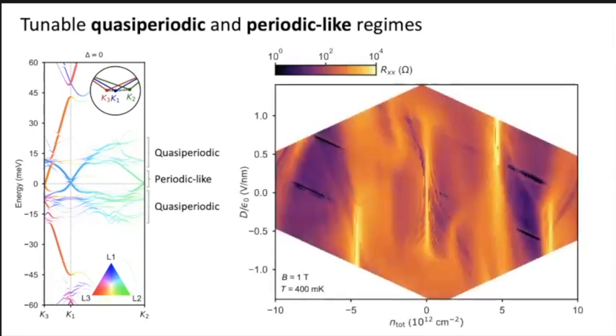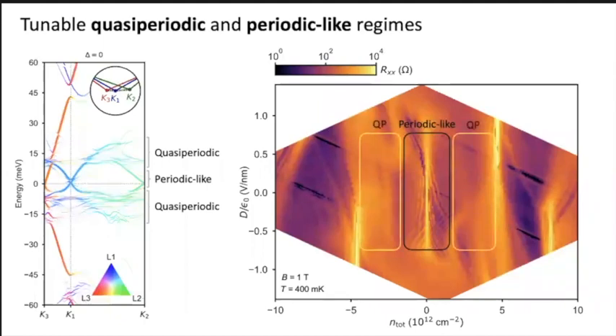If you look again at the quantum oscillations, resistivity versus displacement field and density in a finite magnetic field near zero Fermi energy, near charge neutrality, the system exhibits three sets of periodic quantum oscillations, because the system sees these three periodic-like electronic structures. If you go away in Fermi energy to this region, then these quantum oscillations mostly disappear. Only the one that corresponds to this fast band, which is still present there, remains.